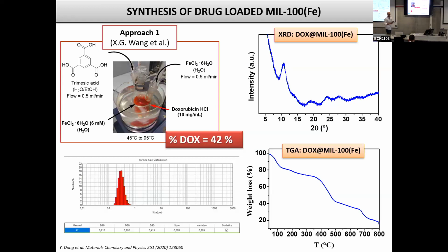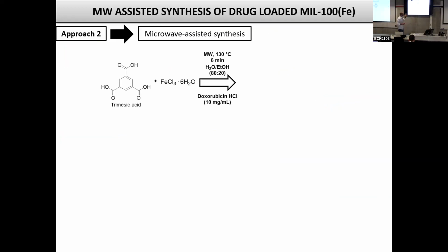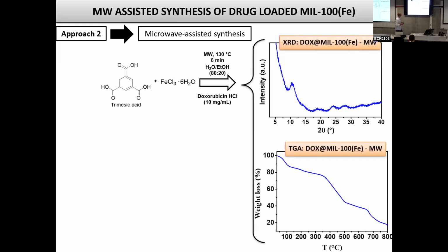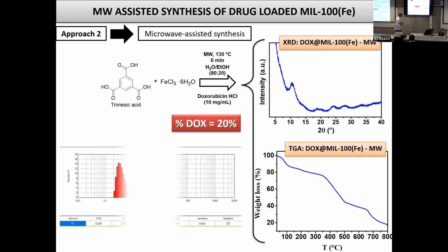That for biomedical application is not so good, but as a first attempt, it should be acceptable. So we tried the synthesis of the same system with microwave assisted synthesis. We also in this case obtained good results from the structural point of view, but the drug loading was lower, with only 20% of the drug loaded.